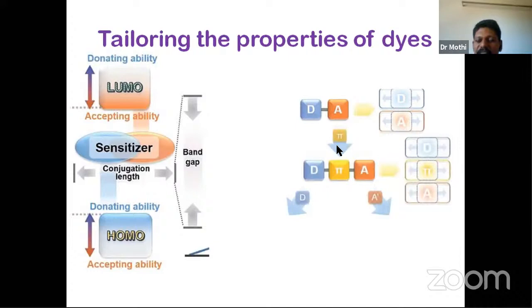Then we can increase the pi system. We can introduce between the donor and acceptor a pi system. Pi system is the conjugation. So in this way, what happens? We can reduce the band gap. And also now we have got a flexibility that we can change three things. We can change the donor, we can change the pi system, and we can change the acceptor. If we can modify a single component and see what is the effect of each component for the DSSC device, we can finalize or choose the best performing dye.